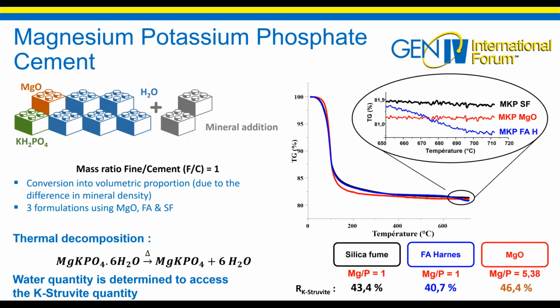To verify the role of the excess magnesium oxide, we had the idea to compare three identical formulations. The only difference is the fines used. We have a mass ratio of fines to cement equal to 1, and we use the previously used fines and magnesium oxide as a reference. I recalculated the molar ratio of magnesium to phosphate for the matrix with magnesium oxide. It is another stoichiometric matrix with a molar ratio of magnesium to phosphate equal to 5.38. The decomposition of struvite occurs at 100 degrees Celsius, which releases 6 molecules of water. The yield of struvite is then calculated.